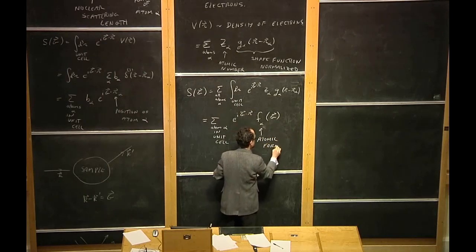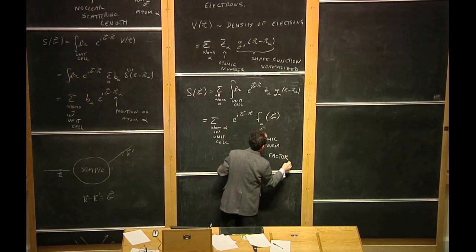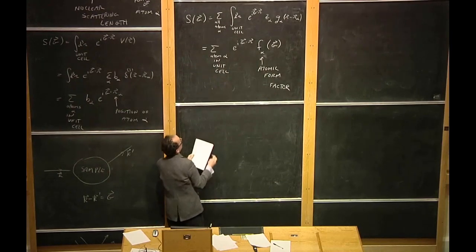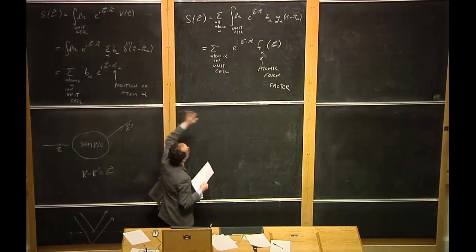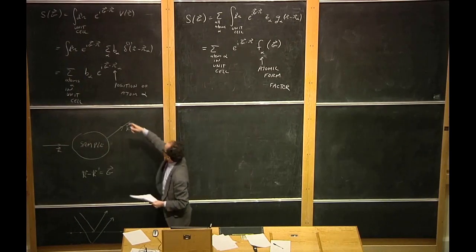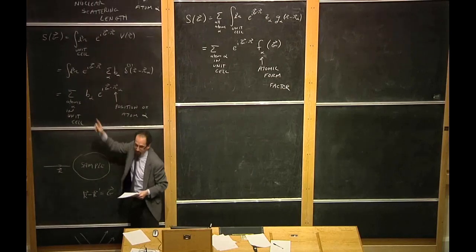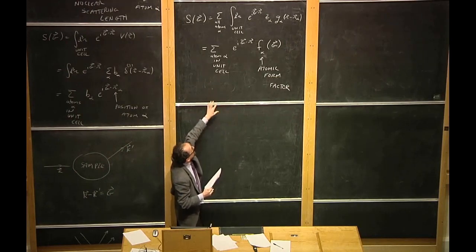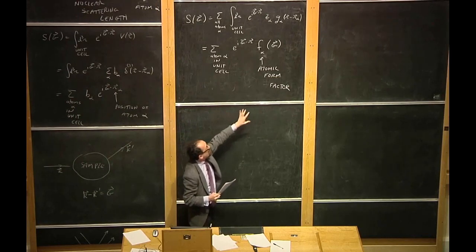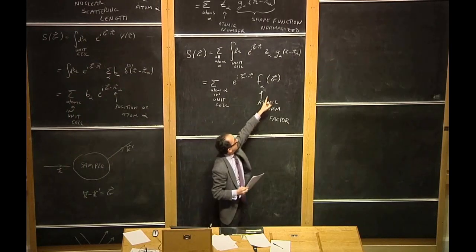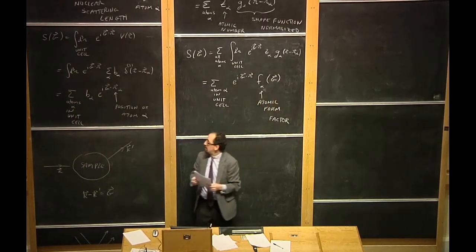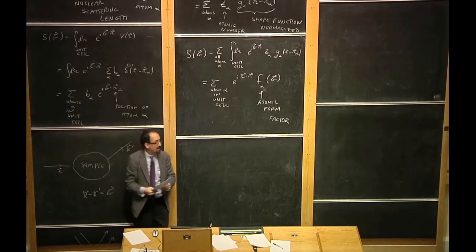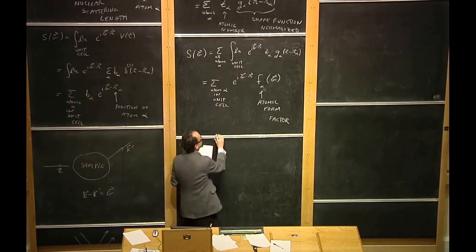Form factor. It depends on the type of atom we're talking about. And maybe just compare it to over here. The atomic form factor takes the place of the nuclear scattering length over here, takes the place of the b alpha. But the overall structure of the structure factor in this equation stays pretty much the same. The only difference is the atomic form factor is also a function of the reciprocal lattice vector g, whereas over here it's not. The reason it's not over here is because we have a nice simple delta function interaction over here, and we have a more complicated interaction over here.